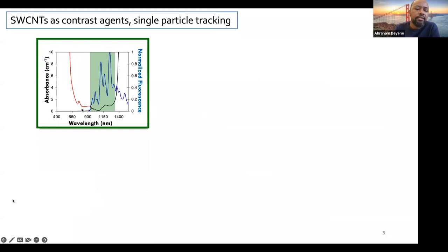is encapsulated in this image that I show you here, which shows the fluorescence emission from nanotubes in this blue trace, overlaid with absorbance by blood, shown here in the red trace, and absorbance by water, shown here in the black trace. And you can see that this fluorescence emission straddles this boundary and targets this local minimum that translates into some advantages for imaging.